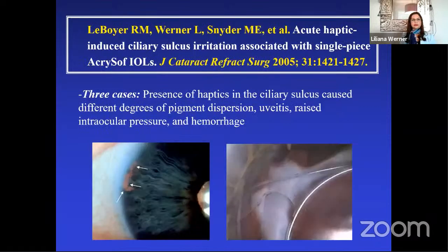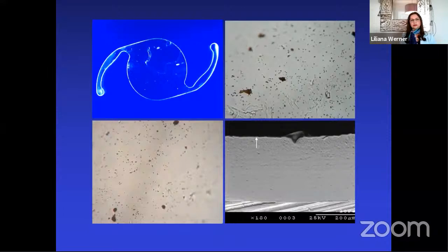It is always important to highlight that single-piece lenses with thick haptics, square and irregular edges, are not appropriate for sulcus fixation, as they can cause pigmentary dispersion, uveitis, increased intraocular pressure, and bleeding. Here, scanning electron microscopy shows that this single-piece hydrophobic acrylic lens has thick haptics with square and irregular edges.